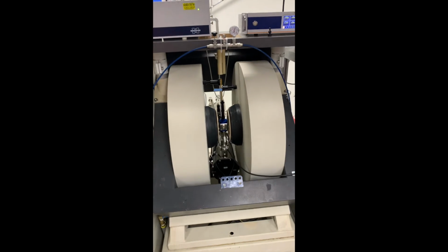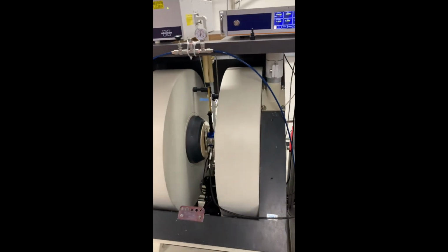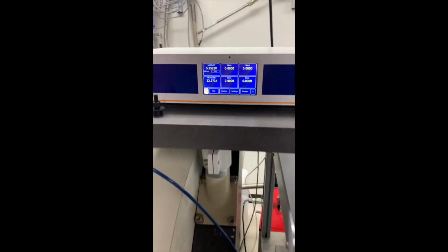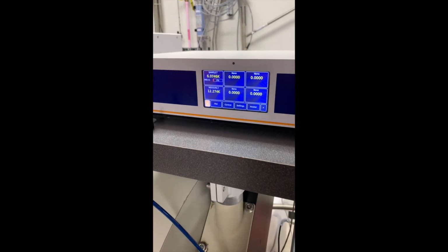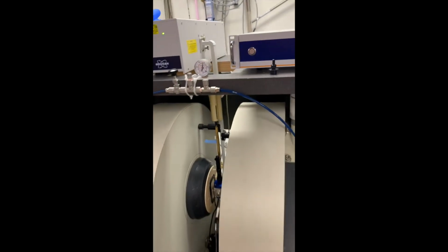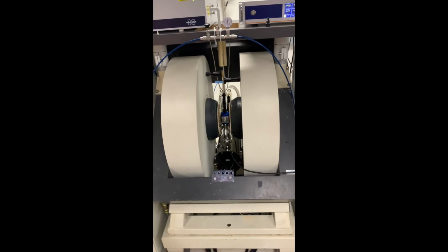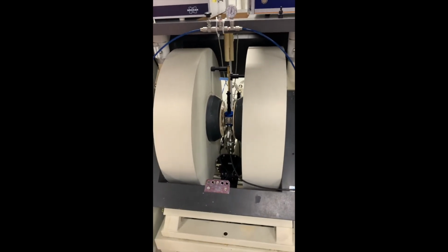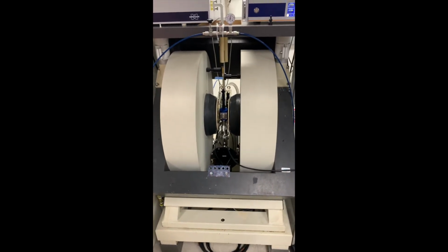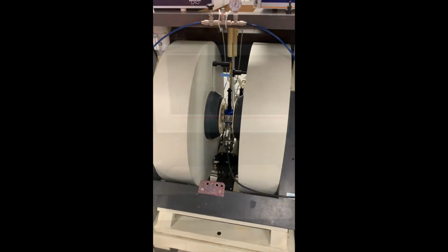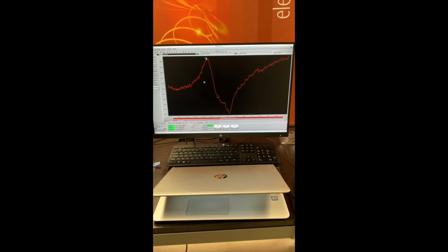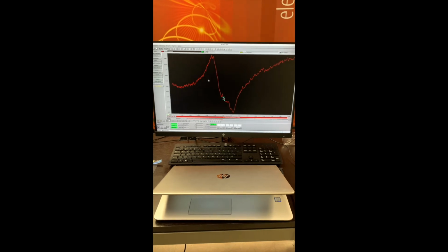This EPR setup is quite unique because it can go to cryogenic temperatures. So typically what I run at is about 6 Kelvin. And so at 6 Kelvin, we're able to study this boron-doped Czochralski silicon because the boron acceptors are frozen out at that temperature. So this is what electron paramagnetic resonance data looks like when you're taking it.